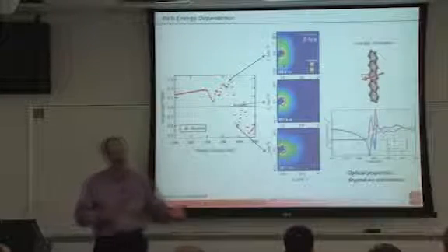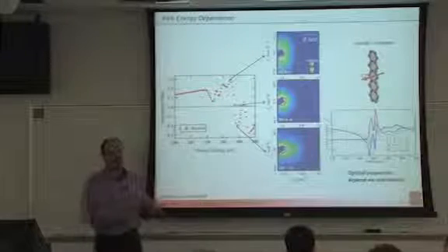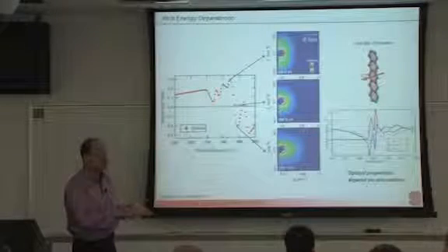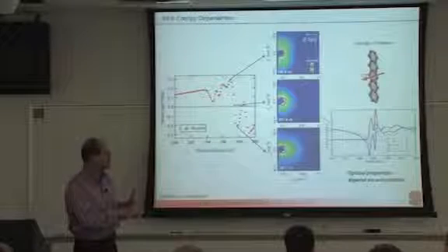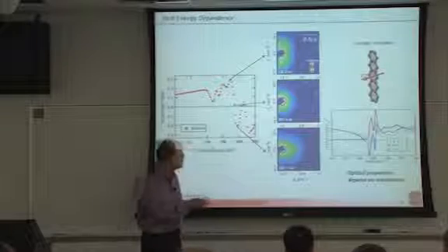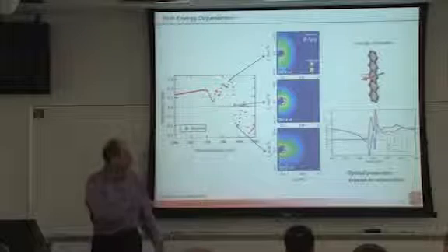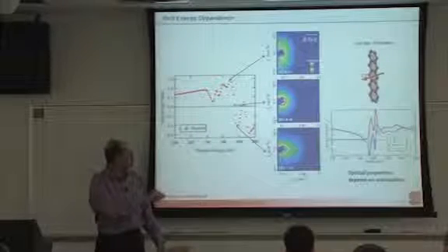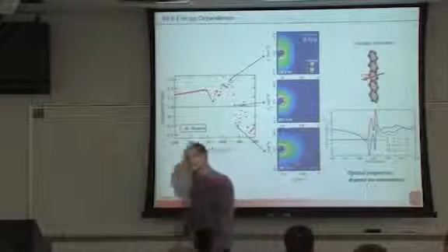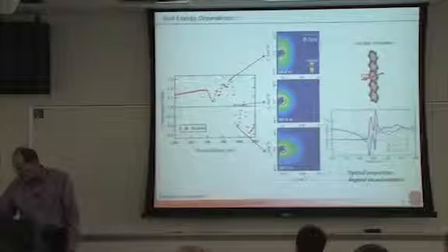In the X-rays, because I start from a spherical orbital at the 1s level, the dipole transition moment is perpendicular to the plane of the molecule. Now, when I look at the absorption, of course, that changes, and via the Kramers-Kronig relationship the real part of the index of refraction as well. So I'm very sensitive to this orientation as a function of photon energy, both at absorption edges, but also below the absorption edge through the difference in the real part. And so that's where the anisotropy below the absorption edge comes from.